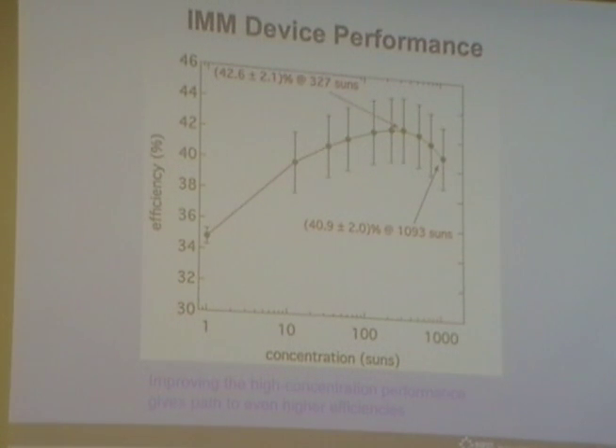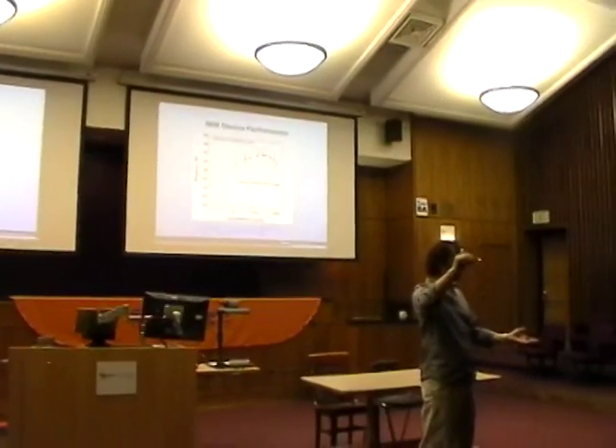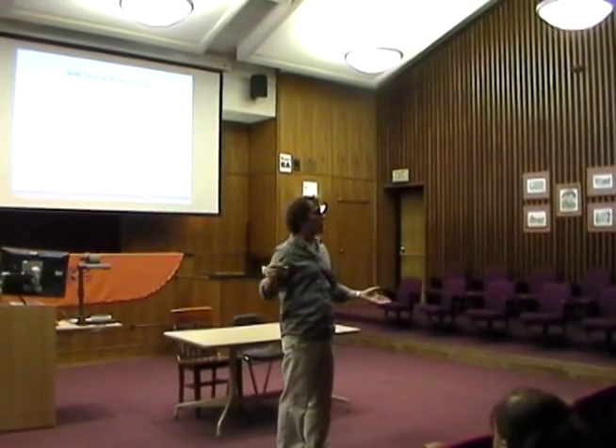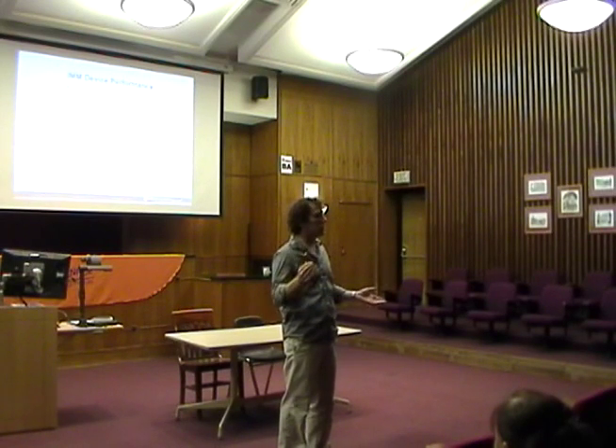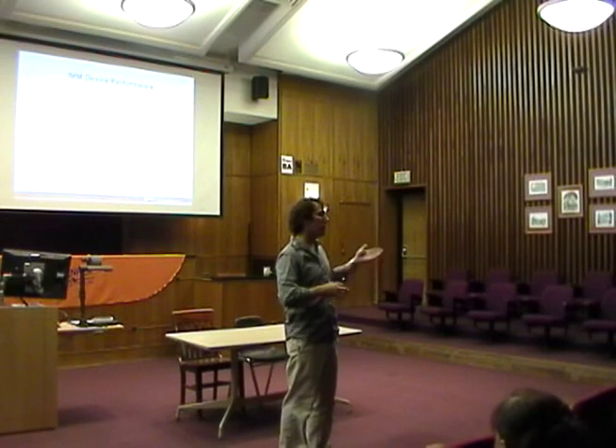The absorption is going up linearly, but if you look at the diode curve, it's an exponential. If you try to figure out how much recombination current you need to exactly balance the absorption, that number increases with voltage. So at higher concentrations, you need more voltage to develop enough recombination current to exactly balance the absorption, and so your open circuit voltage goes up.